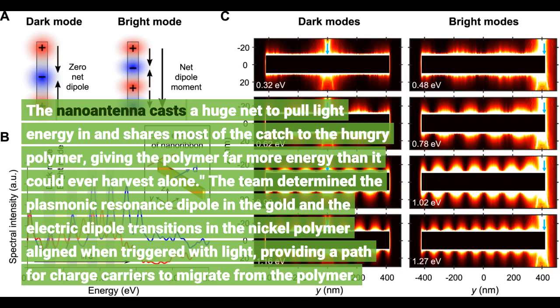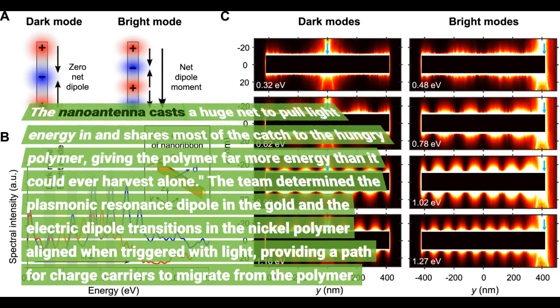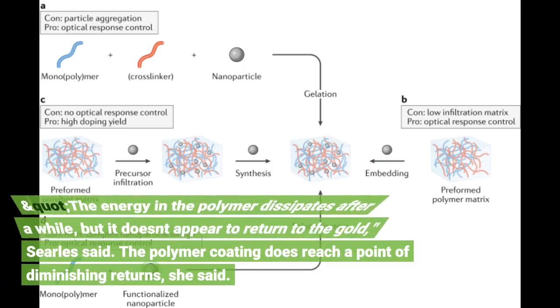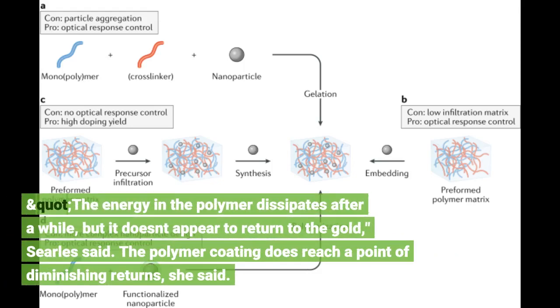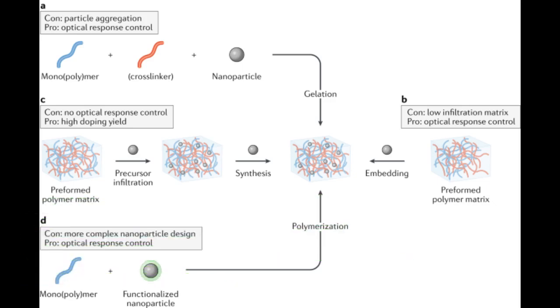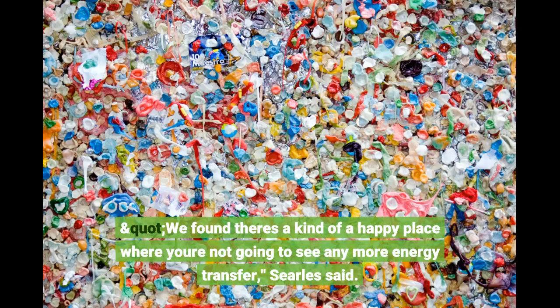The team determined the plasmonic resonance dipole in the gold and the electric dipole transitions in the nickel polymer. The energy in the polymer dissipates after a while, but it doesn't appear to return to the gold, Searles said. The polymer coating does reach a point of diminishing returns, she said. We found there's a kind of a happy place where you're not going to see any more energy transfer, Searles said.